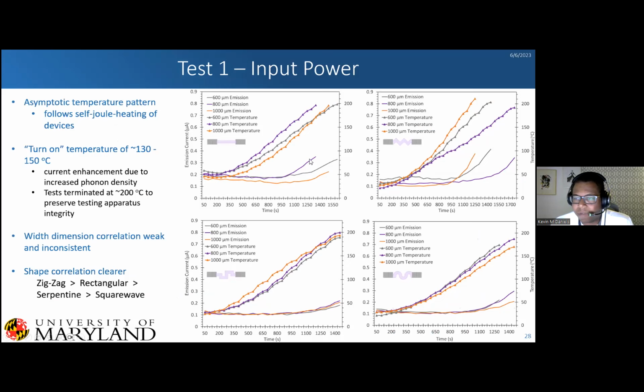And interestingly enough, all of these devices tended to take off in terms of emission at a little less than 150 degrees C. And so this is something that's repeated through all of our devices. That seems to be the turn-on temperature. So there does seem to be at least a little bit of a temperature requirement compared to the truly suspended samples.